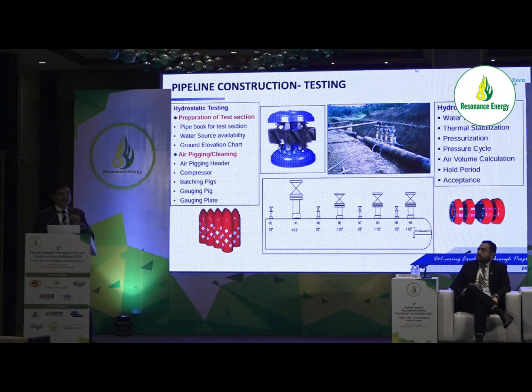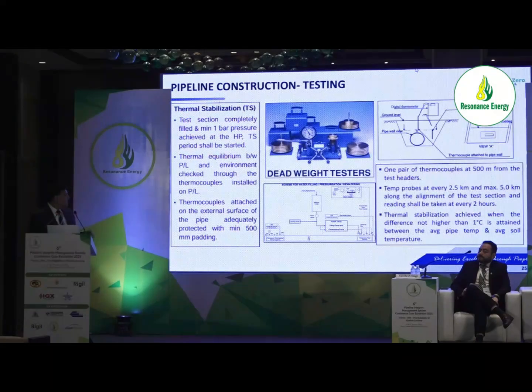For that, there is a calculation in the hydro test specification. How much air is acceptable in that section? That is only 6%. So accordingly, you have to fill the section, then you have to thermally stabilize the pipeline. For that, you have to install the thermocouples. If you see the thermocouples, how you install, how much distance it has to be installed, and how you can say that the pipeline is thermally stabilized? When the difference between the average temperature of the soil and the average temperature of the pipe is 1 degree, then you can say the pipeline is thermally stabilized.